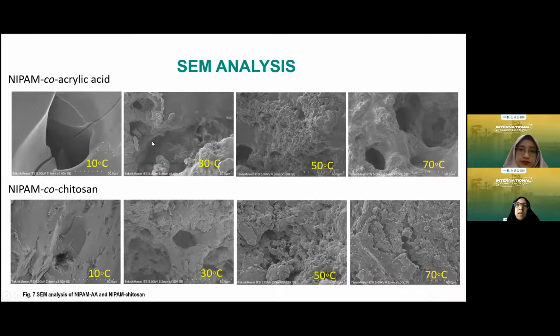The SEM analysis shows the morphological structure of the NIPAM-co-acrylic acid and NIPAM copolymerized with chitosan before they are blended together. As we can see, in various synthesis conditions from 10, 30, 50, and 70, more porous forms in the gels. The porous structure is also obtained in the NIPAM-co-chitosan with increasing temperature of synthesis. The higher or bigger pores can occur because when we synthesize at higher temperature, the NIPAM tends to shrink. That condition is immiscible, so the gels form pores and aggregate.